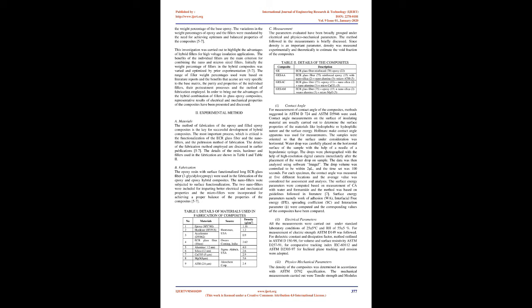2. Experimental method. A. Materials. The method of fabrication of the epoxy and filled epoxy composites is the key for successful development of hybrid composites. The most important process, which is critical, is the functionalization of the ECR glass fiber and the nanofillers, and the pultrusion method of fabrication. The details of the fabrication method employed are discussed in earlier publications 5 to 7. The details of the resin, hardener, and fillers used in the fabrication are shown in Table 1 and Table 2.